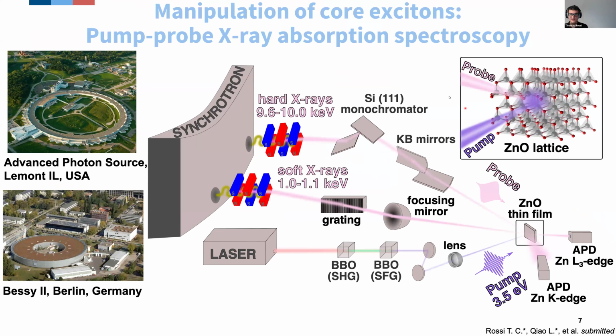So the experiment we did is this one. This is a schematic of the experiment we did. It's actually highlighting two different experiments we did at two different synchrotron facilities. What these two experiments have in common is that we did measurements on zinc oxide thin films. And the zinc oxide thin films are excited by an ultraviolet pump pulse. There is one experiment where the probe pulse is made of hard X-rays. That's an experiment that was done at the 7-ID-D station of the Advanced Photon Source. With these hard X-rays, we are resonant with the zinc K-edge.